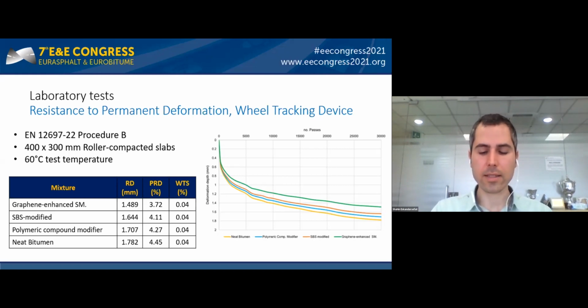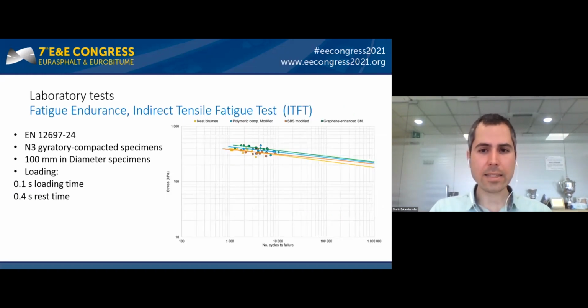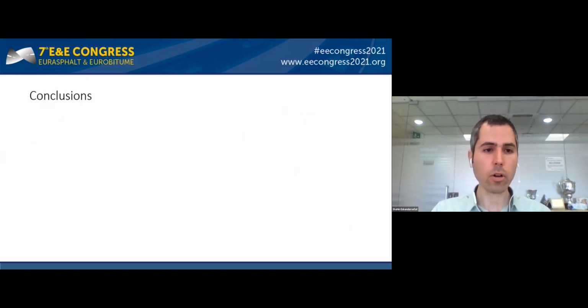This could be expected since during the ITSM modulus testing and HWD testing, we have seen higher stiffness for the mixture containing asphalt supermodifier. And the last test was fatigue endurance, done according to European standard number 24 by means of the indirect tensile fatigue test. You can see according to this plot, the mixture containing graphene enhanced asphalt modifier showed significantly better results when compared to the reference neat bitumen, and comparable or better results when compared to the commonly used SBS-modified mixture. And conclusions.